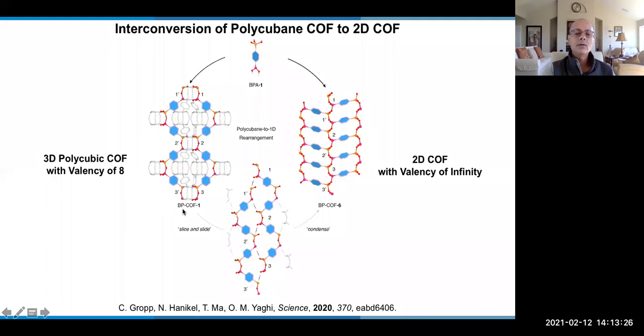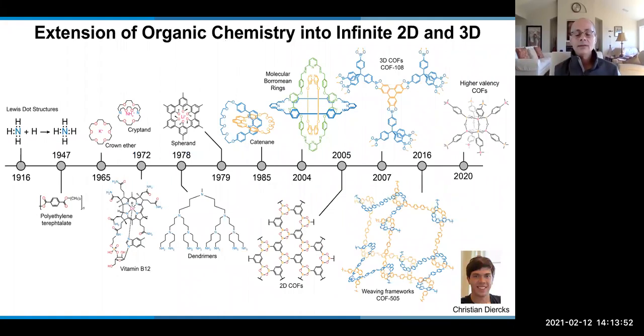And this is very nicely, we call it the slice and slide mechanism, where every pair of phosphorus and boron is cleaved from the other pairs in the cube, and then these chains slide with respect to each other to make the COF with the infinite valency. So that's how you get higher than valency 3 or 4, and this is sort of a chronology of the power of the covalent bond, running from the Lewis concept of the covalent bond to the creation of polymers and host-guest complexes, total synthesis. All of this is based on covalent chemistry, of course, the introduction of catenanes.